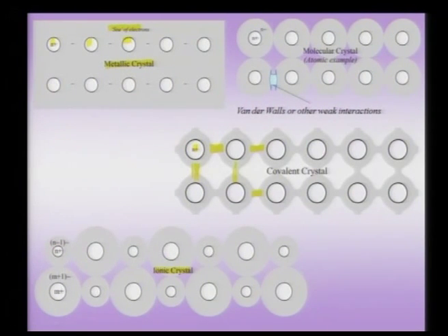Now, we also talked about something known as the molecular crystal, and in that case, as you know, these individual entities are molecules, which I am shading here. So, this would be a molecule, for instance, and now the interaction between the molecules is of a weak type. There is a weak interaction which is actually leading to the formation of a crystal. Typically, because the interaction giving rise to the crystal is weak, the melting point would be lower, and this is a characteristic of molecular crystals.